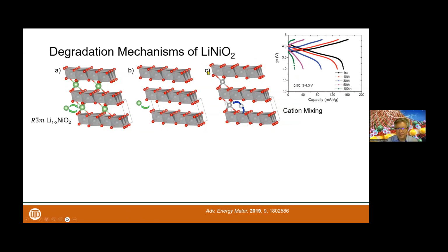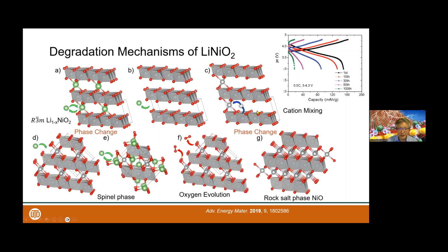This is based on the actual experimental data we obtained using pure lithium nickel oxide. We have done the synthesis. If you do 100 cycles, the capacity is rapidly degrading. This is, of course, well known in the community, so this is not the first time we are showing that, but the point is that we have done the theoretical analysis and corresponding characterization of what's happening.